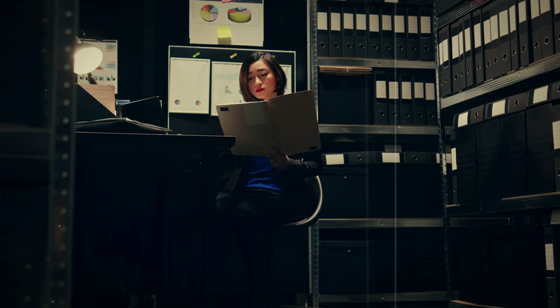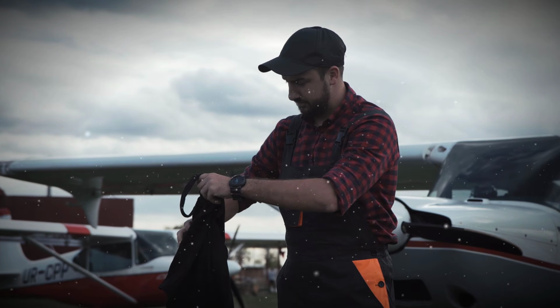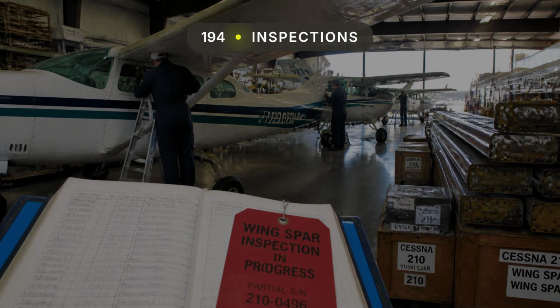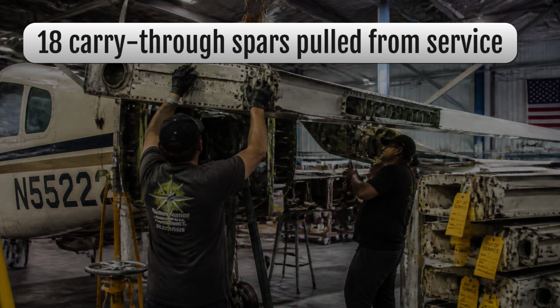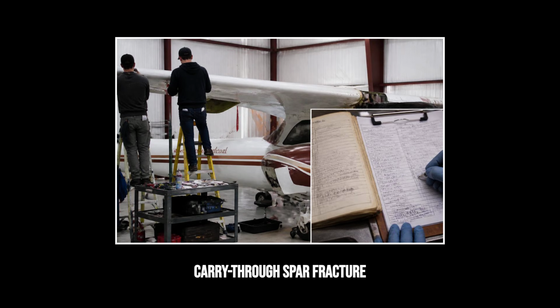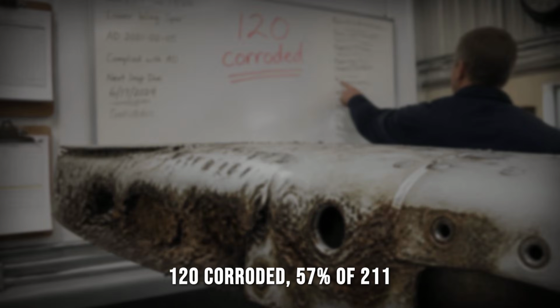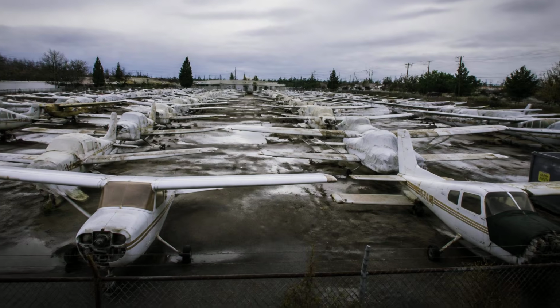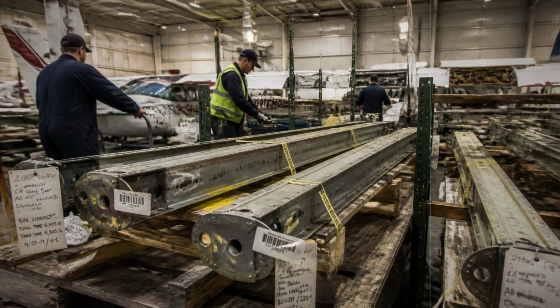The FAA opened an airworthiness concern sheet within weeks. The inspection data that came back was not encouraging. Among the 194 initial inspection reports on early model 210s, 95 aircraft showed corrosion, 49% of the fleet inspected. Inspectors pulled 18 carry-through spars from service. Among the 211 Cessna 177 inspection reports the FAA received, 120 showed corrosion, that is 57%. 14 Cardinals had their spars removed from service.